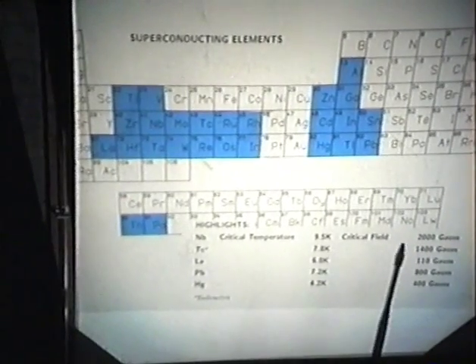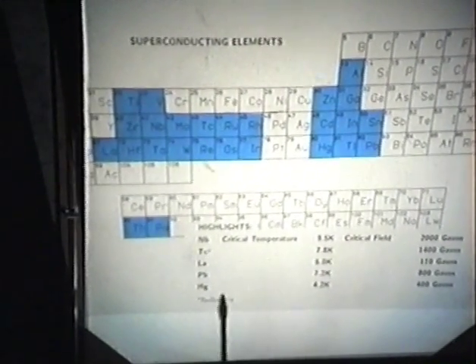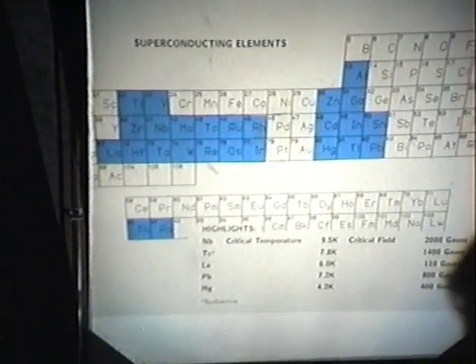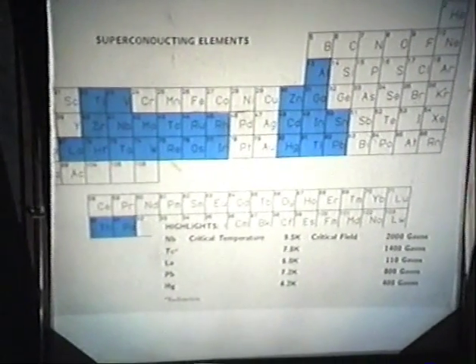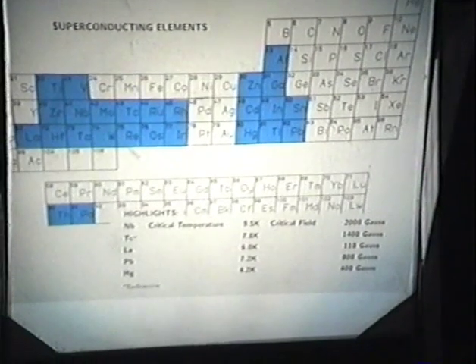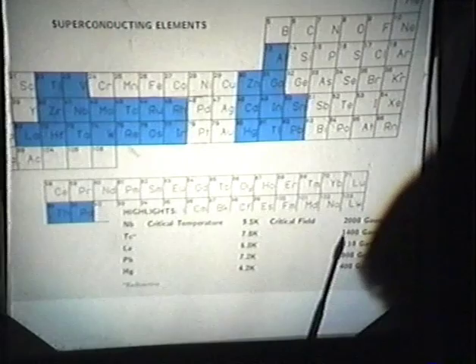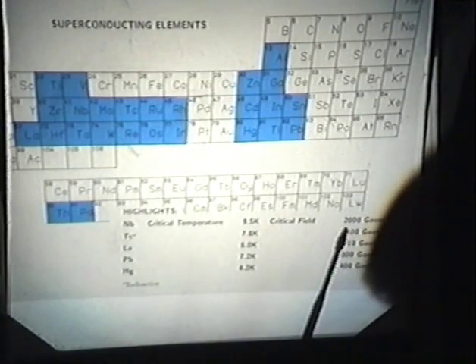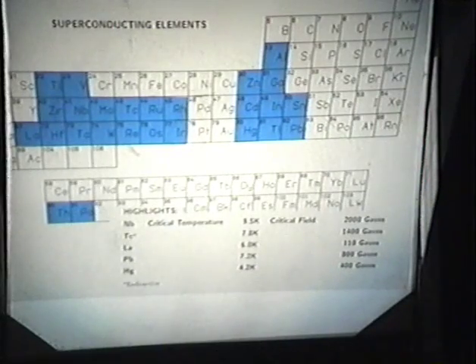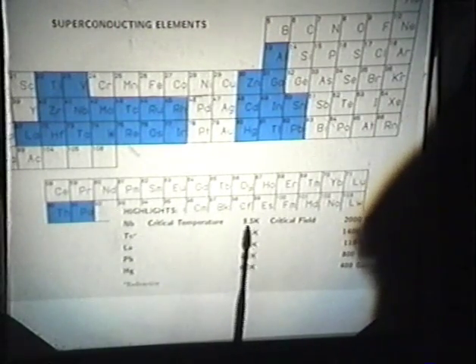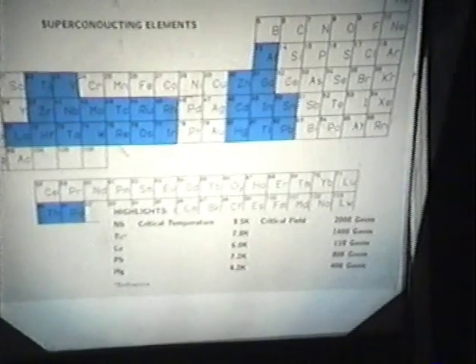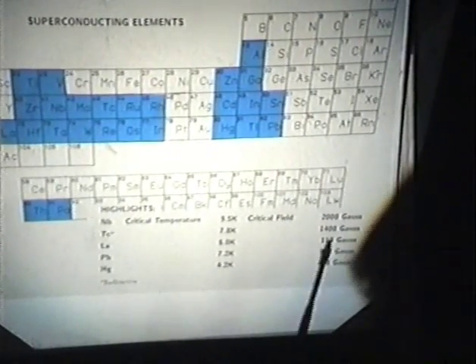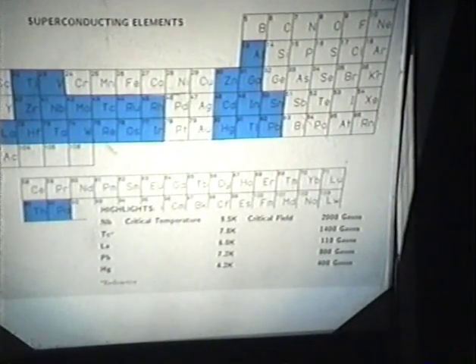And again, this table is only the edited highlights. We find that the best one is niobium, into which you can put 2 kilogauss, which is 0.2 of a Tesla, before you destroy the superconductivity. And I wouldn't really get excited about a magnetic field of 2 kilogauss. I can do that with an iron electromagnet dead easy without having to cool it down to 9.5 Kelvin. So this was a tremendous disappointment.